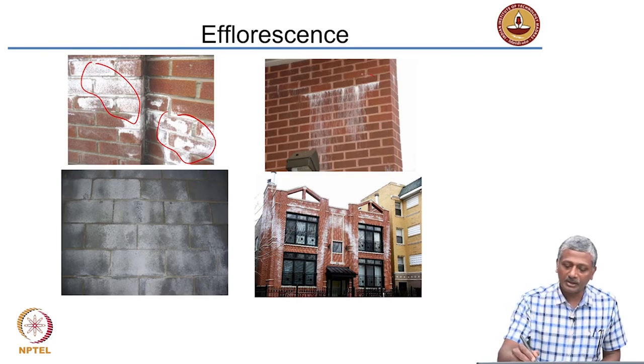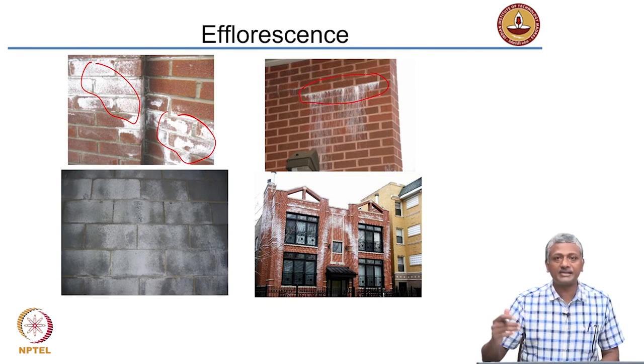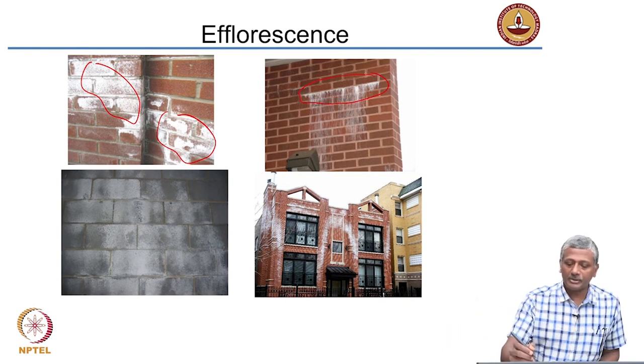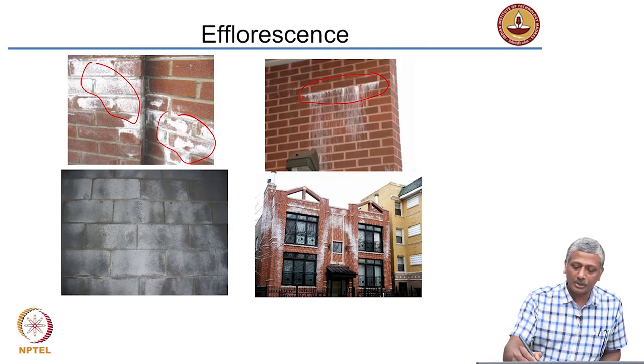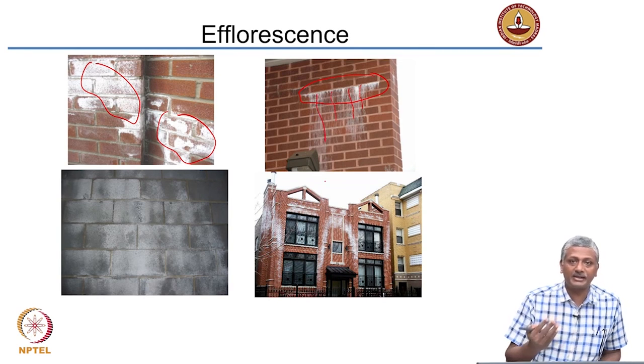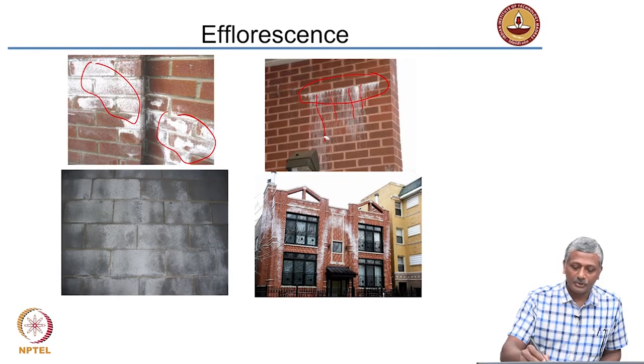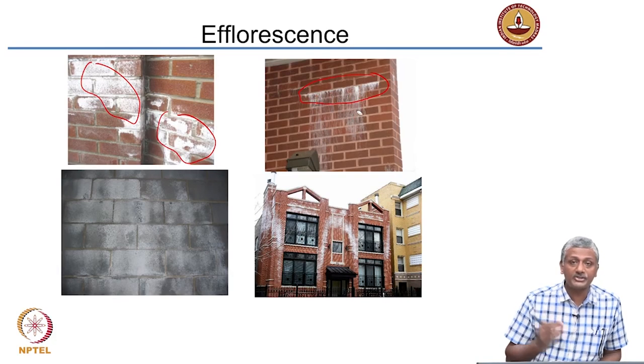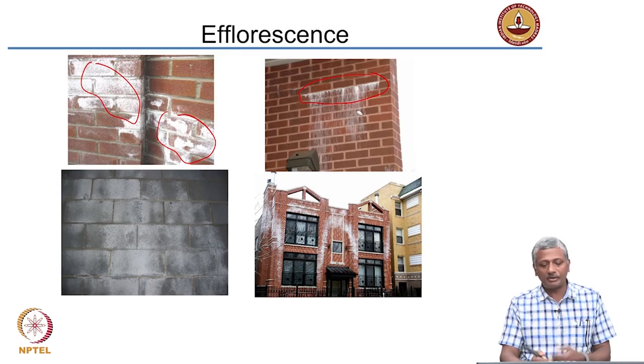Now here you can clearly see a telltale sign of water that is coming out from inside, because all the salts seem to have originated only from this particular line there, right? All the salts seem to have originated only from that line, and then as the water drips down the building and dries out, the salts are basically getting deposited. So you see that this is a case of water leakage from inside the building which is carrying the salts out. But this is also called efflorescence.